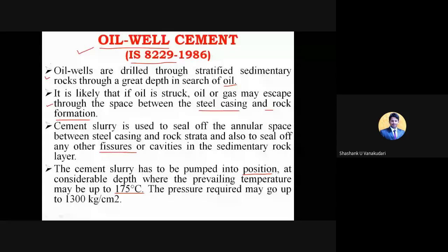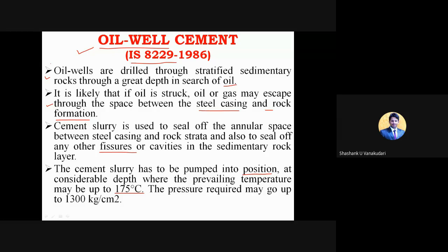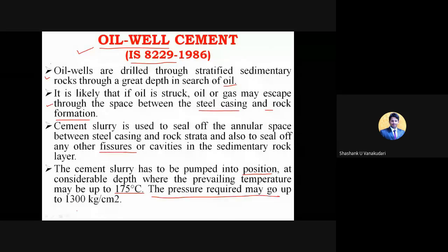So that's the depth we need to penetrate. Where we reach the strata is the place where we need to stop penetrating or start digging. At that location, the temperature will be 175 degrees Celsius. At that temperature, we need to place this oil well cement, right? The pressure required there may go up to 1300 kg per centimeter square.